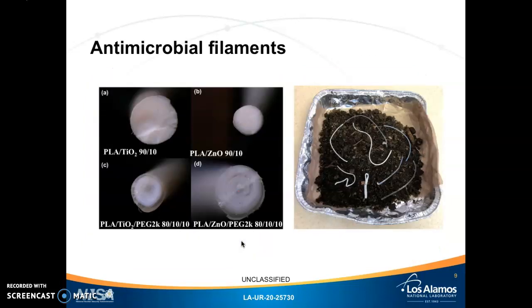The images on the left are cross-sections of the multifunctional antimicrobial filaments. We observe an outer crust developing, which becomes more pronounced when PEG is added, along with some concentric patterning within the filaments. This work is currently ongoing, and further developments will yield insight into this phenomenon.